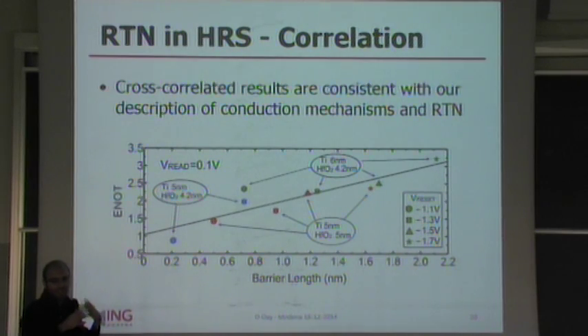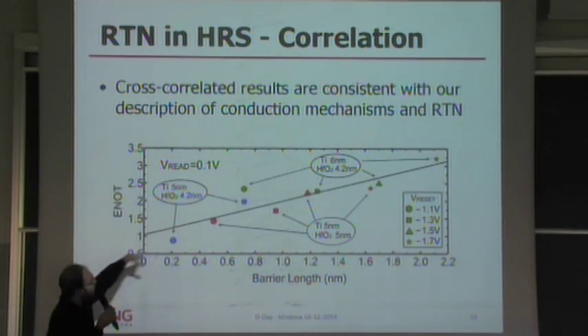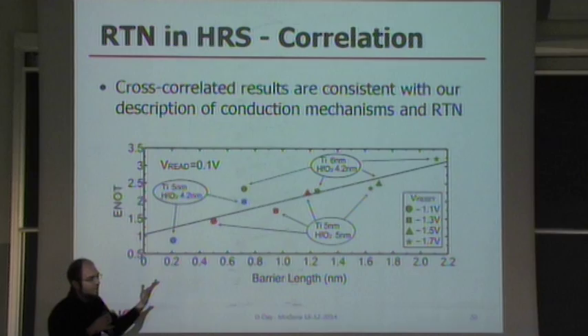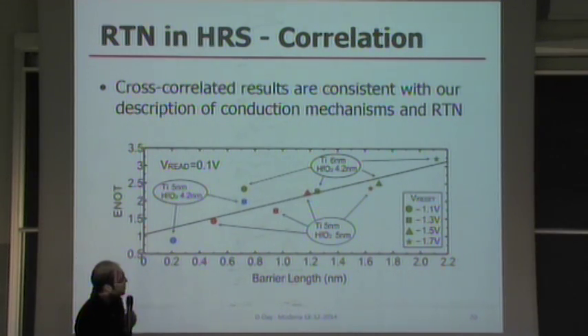And if these defects get activated and deactivated, I have statistically more complex RTN because of more defects contributing to my RTN signal. And this is really interesting. So this really depends on the barrier thickness, and that's it.